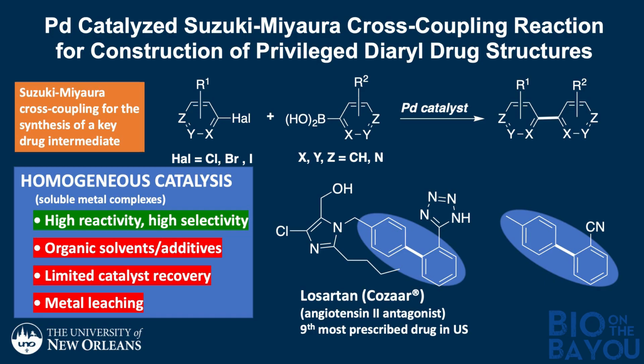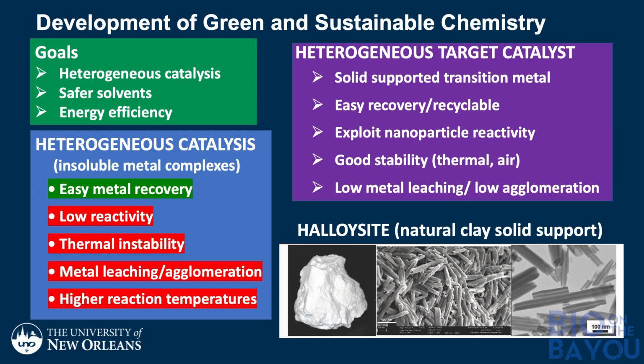Okay. So our goal was to develop a heterogeneous process that could function as a reactive catalyst. Now, essentially, heterogeneous catalysis is great from a green chemistry point of view because you can isolate the catalyst very easily. It just filters out of the reaction mixture. It's not soluble. But limitations include low reactivity, thermal instability, metal leaching, and agglomeration. This is the metal clumps together and basically becomes unreactive. And of course, then to get these reactions to go, you have to use higher temperature.